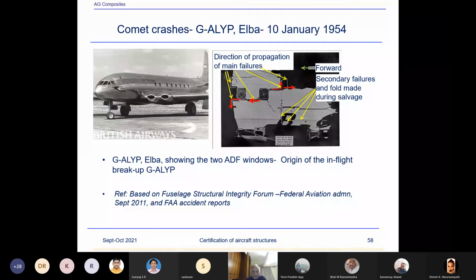Okay, the issue was with one of the Comet failures here after investigations. I've taken the picture from the failure investigations. What you see here are the cracks around the window. There is a square window, with high stress concentration in the corners, as you would know. Normally, you would not like to design a window with a square. Of course, none of the windows after this are ever square. They're always elliptic.